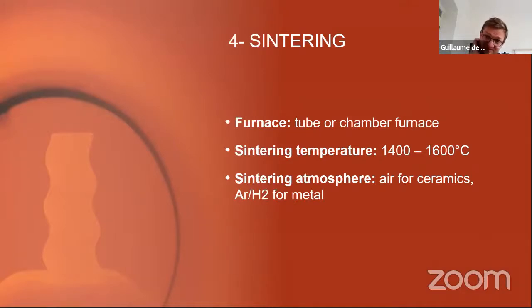We sinter in air for ceramics, and there's a big difference here. When we want to do metal, when we do steel, we need to have a neutral gas. Usually it's argon plus hydrogen. For stainless, sometimes you actually need pure hydrogen, which is quite a problem, which is not something we can do with our furnaces. You need a special furnace. And we are also launching very soon a new steel, a tool steel, which can be sintered under nitrogen. But in any case, you cannot sinter a metal under air because you would oxidize the metal, of course.